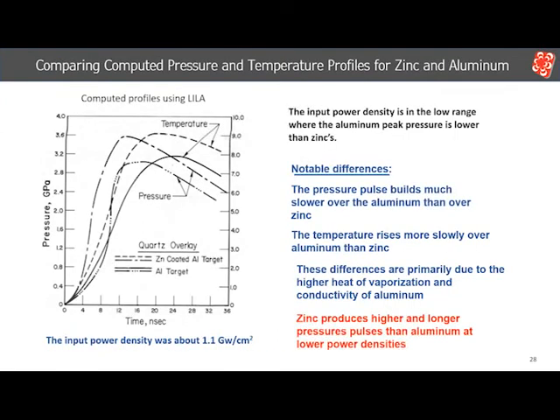To get a better understanding of the observed differences between zinc and aluminum overlays at the lower power densities being used, LILA computations were made for the pressure and temperature profiles at the overlay surfaces. The same triangular laser pulse shown earlier was applied in the computations. In the figure, the two highest profiles are of zinc and the two lower profiles of aluminum. If we compare the pressure profiles, the rate of pressure increase for aluminum lags significantly behind that for zinc.